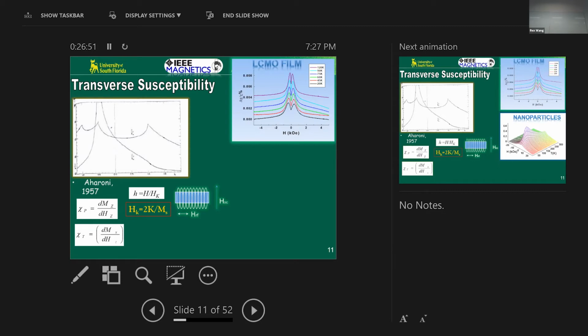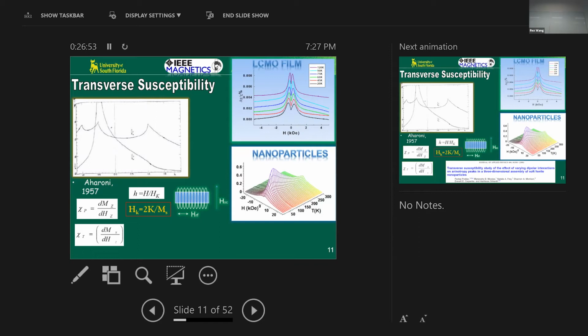If you take nanoparticle assemblies, we can do even better because we do this experiment in a superconducting magnet, so we can follow the entire magnetization dynamics as a function of temperature and field across these superparamagnetic blocking transitions. These nanoparticles are tiny, right? So at high temperature, room temperature for example, if you take these 10 nanometer magnetic particles, they behave like paramagnets simply because the thermal energy, kBT, is higher than the intrinsic magnetic energy. So they are fluctuating, but each one of them is a super spin, so they're superparamagnets.